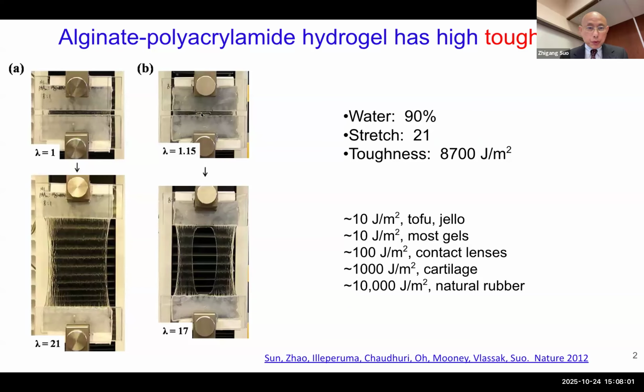And if we make a cut in this material, there's a crack. This is how we measure the resistance to crack growth. We cut a crack and then pull this to watch whether the crack will grow or not. In this case, the crack does not grow. What you are looking at is just the material deforming. The crack doesn't grow, up to a stretch of 17 times. So in mechanics of materials, we have a way to evaluate toughness. This material has a toughness of about 10,000 joules per meter squared.